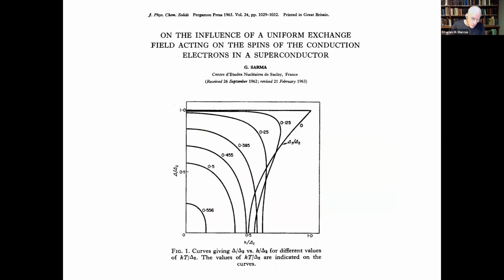Now the theory of this, the order of this transition in which the gap collapses or doesn't collapse depending on the exchange field, and I apologize because every single paper uses different notation for all the quantities, but I'll try to say in words what's going on, is a very old subject, dating back to really only the first years after BCS itself. The study of a uniform exchange field on a superconductor was already being studied. And the important point had to do with how, in this case, temperature affected this transition. You turn up the exchange field. As the exchange field goes up, the gap doesn't care at all until bonk, you kill superconductivity. As you turn up temperature, again, the gap doesn't collapse that much until bonk, it kills superconductivity.